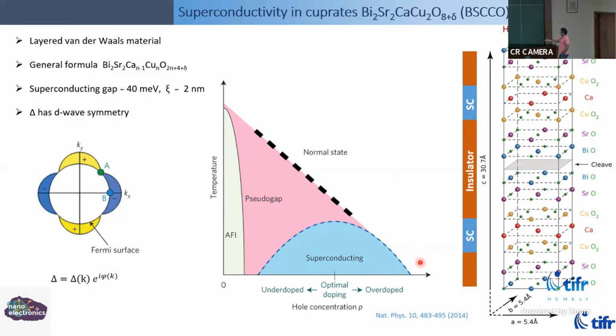I'll show you an experiment which nicely shows that as you tune the oxygen doping, you can map out this whole dome. This was done by another group. The surface atoms are probably the first where off-stoichiometric material exists, but as such, the surface isn't very special.